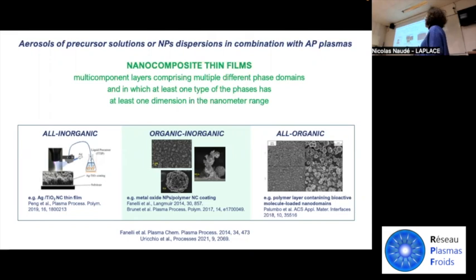The utilization of these precursors can lead to the deposition of nanocomposite thin films, that is multi-component layers that can comprise different phase domains, in which at least one type of the phases has at least one dimension in the nanometer range. And over the last decade, several groups published papers in our community on the preparation of all-inorganic thin films, such as thin films containing TiO2 nano inclusions in a silica-like matrix or silver nanoparticles in a TiO2-like matrix.